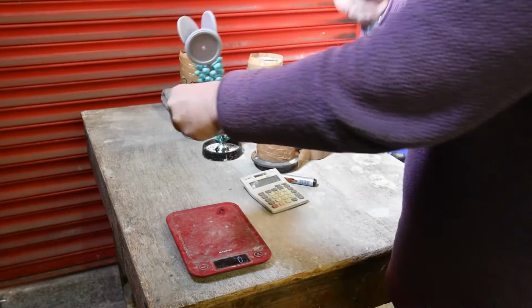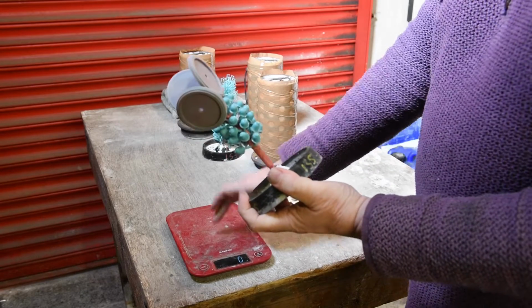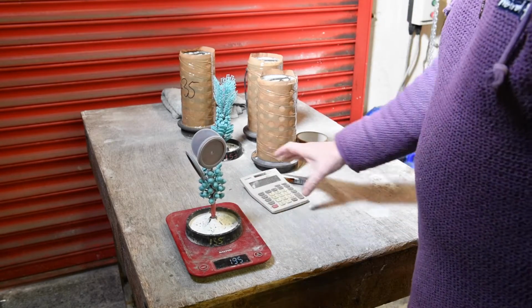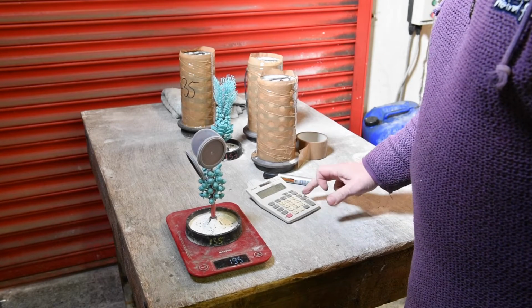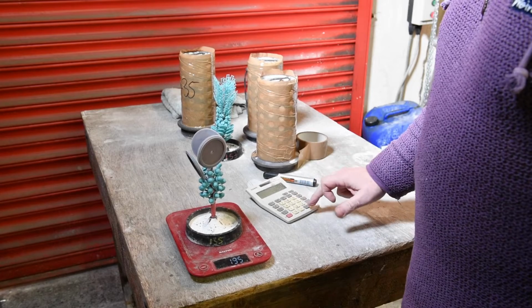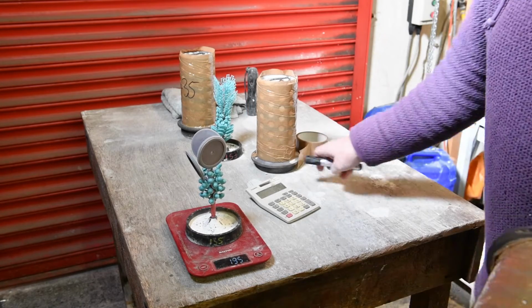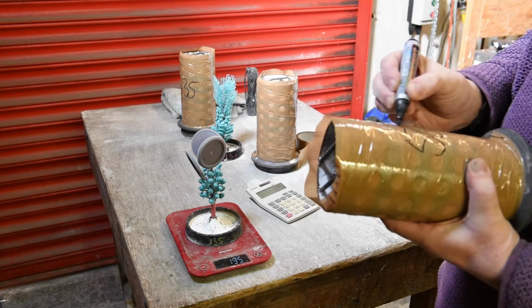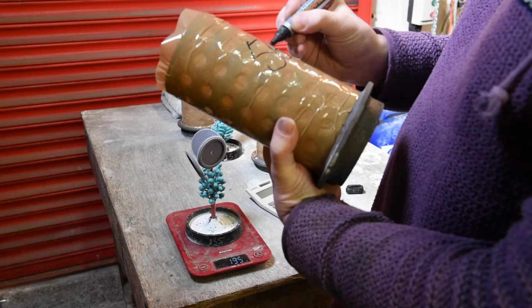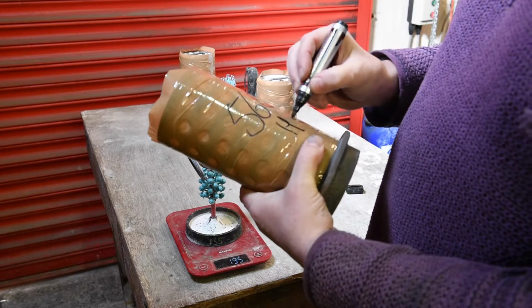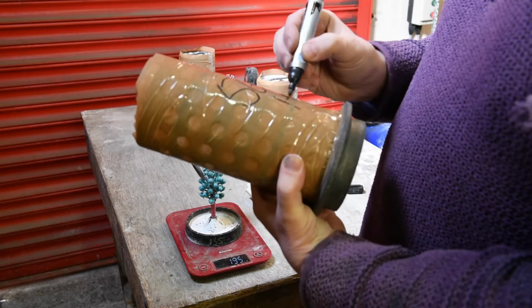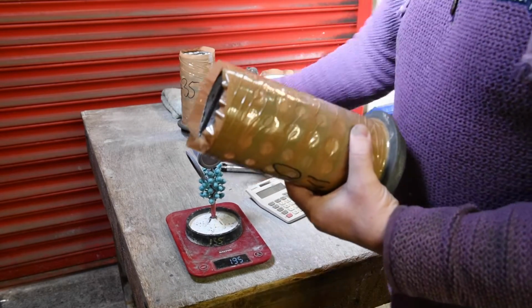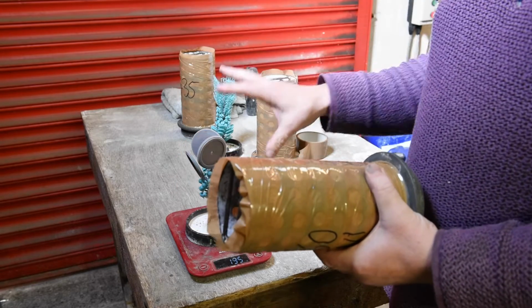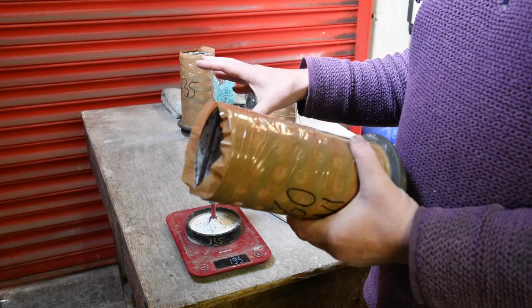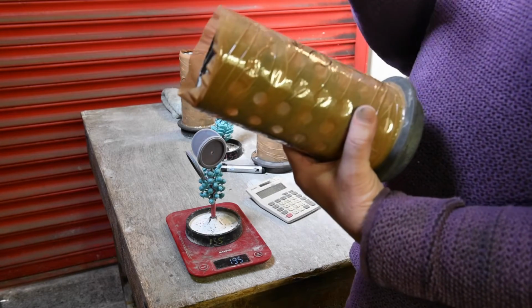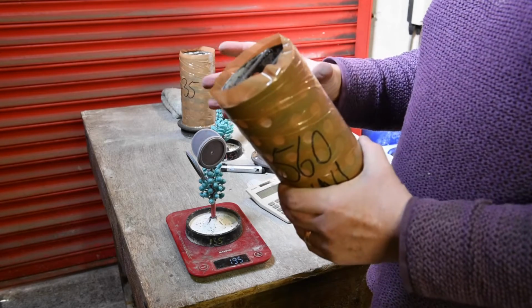So again, now in this one, which has heavy parts in, flask base is 135, so it's 195 minus 135 times by 9 gives us 540 plus 20, which would be 560. But as these are heavy parts, I'll usually put HVY on there just to remind me, because these parts will have to be cast at a lower temperature. Otherwise we'll end up with porosity in the castings. So the actual temperatures of both the metal and the flask will be lower when it comes to cast the parts.